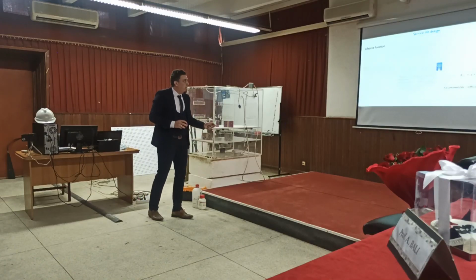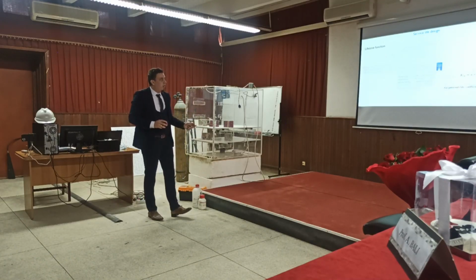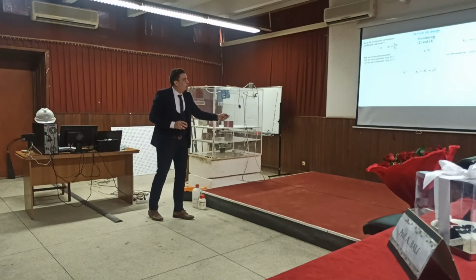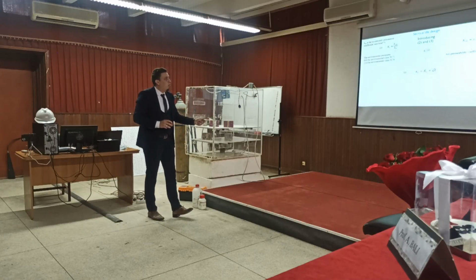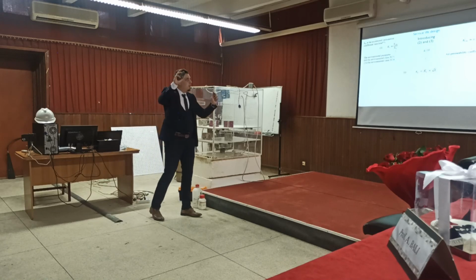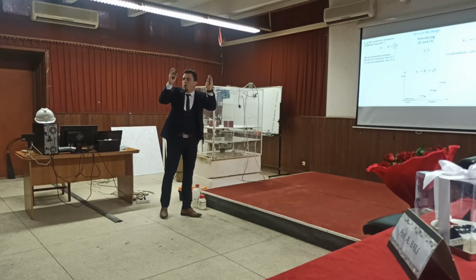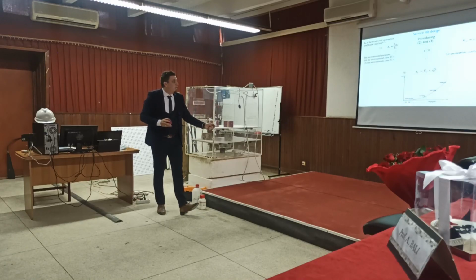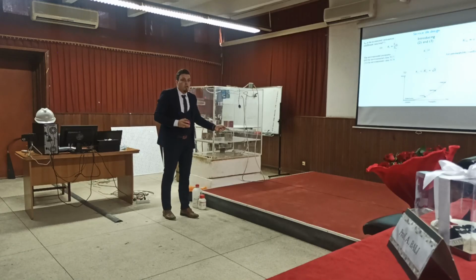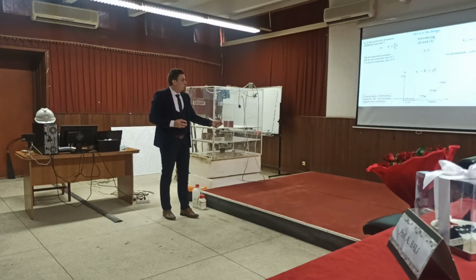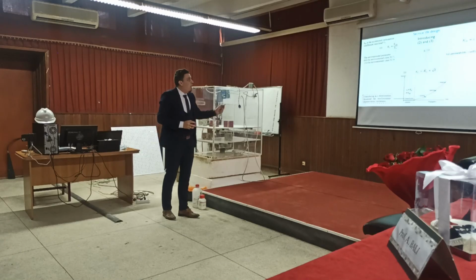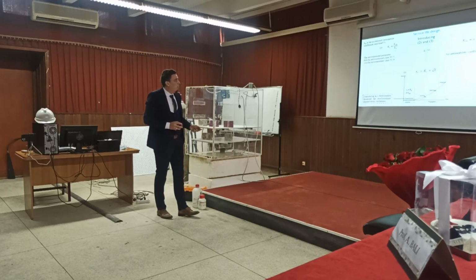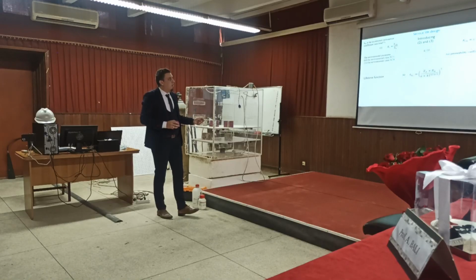This is the relationship. Here you see KCA equals A times KT. This KT is the air permeability coefficient of Torrent, and A is the parameter related to the type of cement. Now, introducing equation 3 and equation 2 into this equation, Fick's first law, and considering something important, that the end of service life of my structure is the reinforcement depassivation, I will not consider the propagation period, just the reinforcement corrosion initiation period. If we consider this, our lifetime function, which is formula 1, becomes this. And this is our basic formula here.